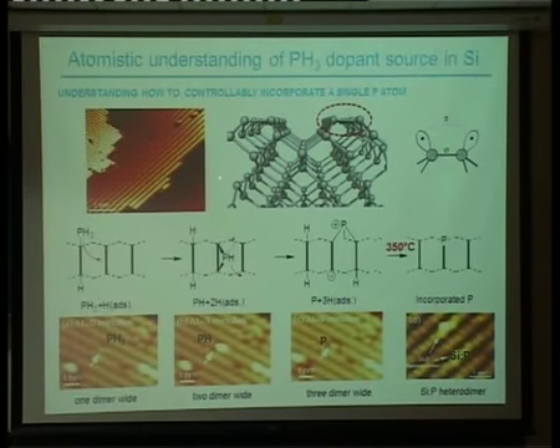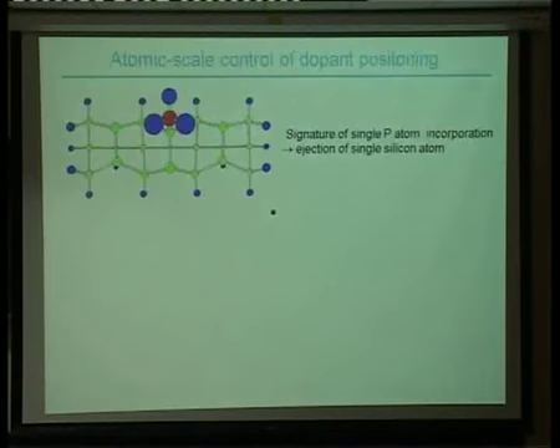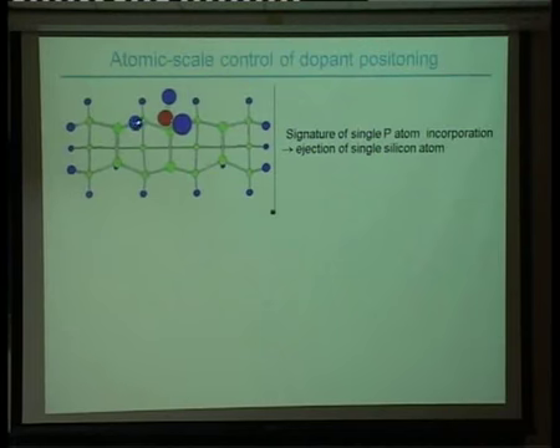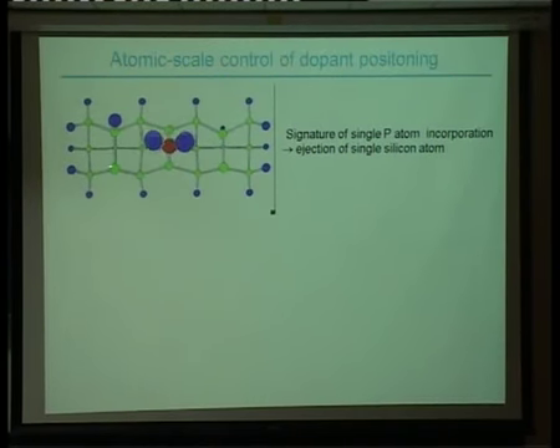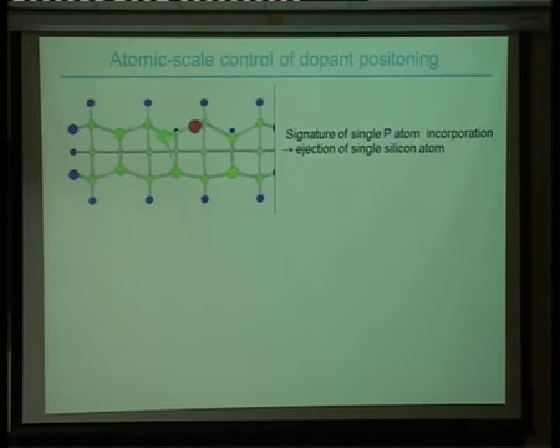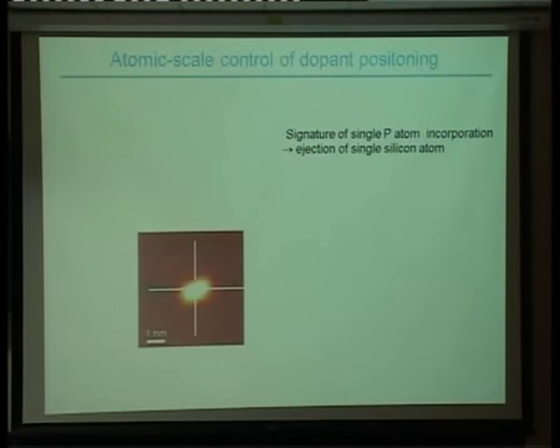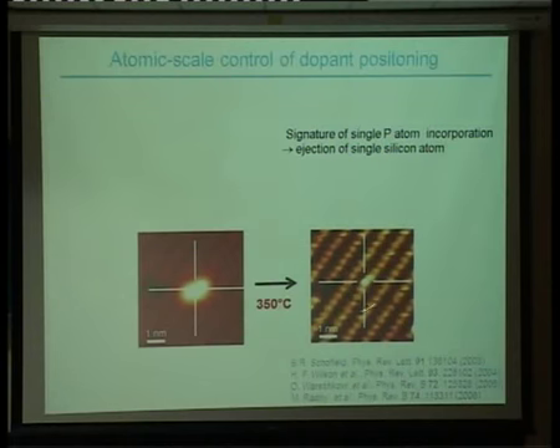Now, the critical part of this is we need to open up exactly 3 adjacent dimers on the surface to allow this chemical reaction to occur. So we have a little movie here showing this chemical reaction. Here's our phosphine molecule. You can see that the hydrogen goes to one side. The other hydrogen comes down to the same side of the silicon dimer. The other one goes across to the other side, and then the phosphorus atom will go in through this end bridge site and kick the silicon atom out. So if you can open up a hole that's exactly 3 dimers wide, you can deterministically put that phosphorus atom in with plus or minus 1 lattice spacing.